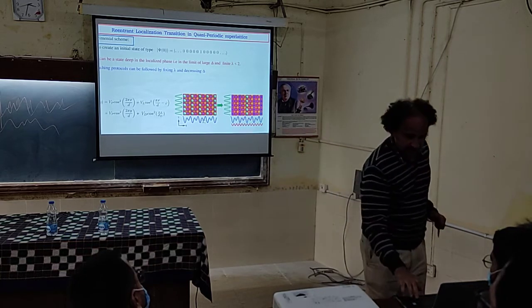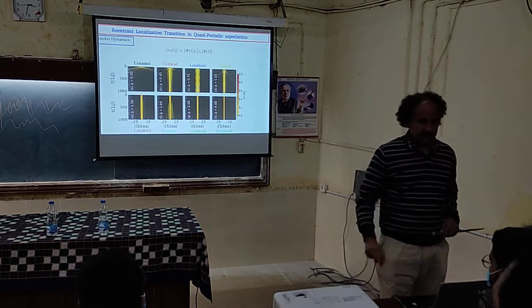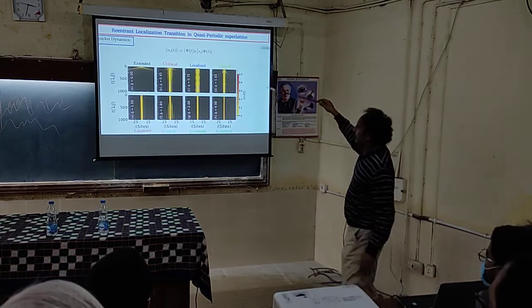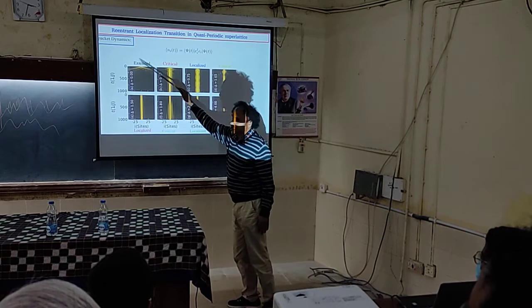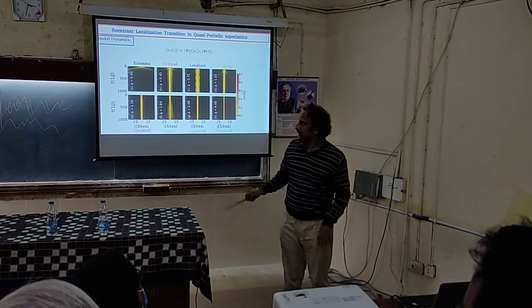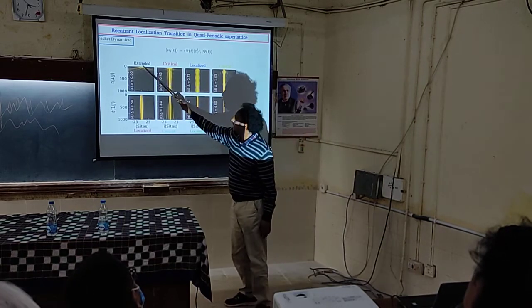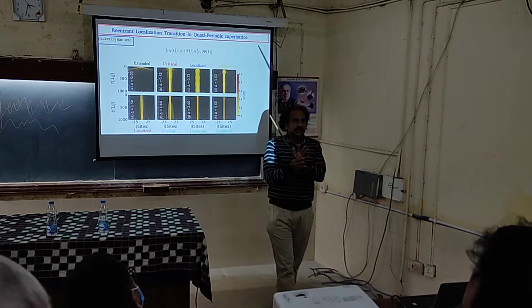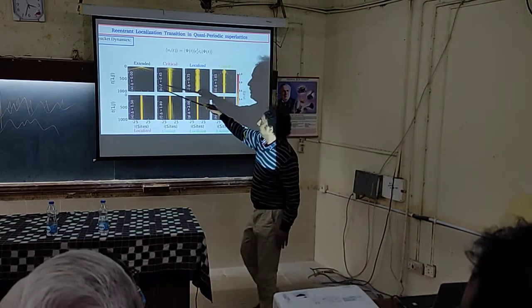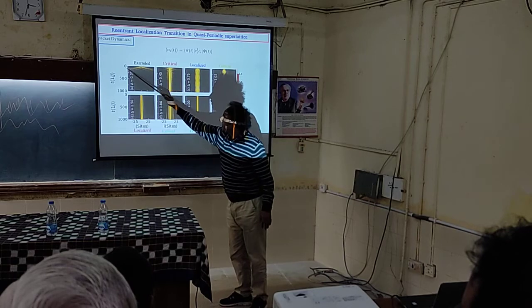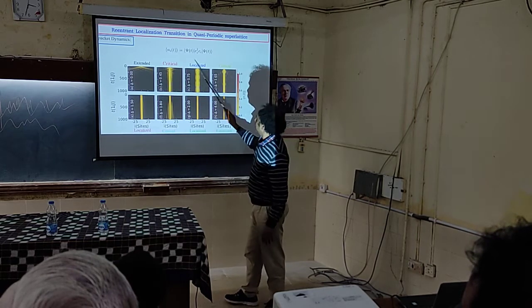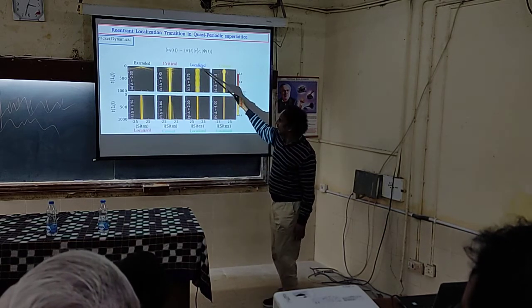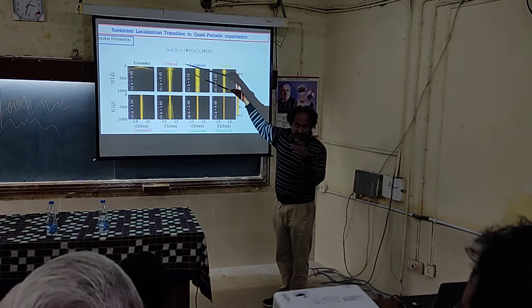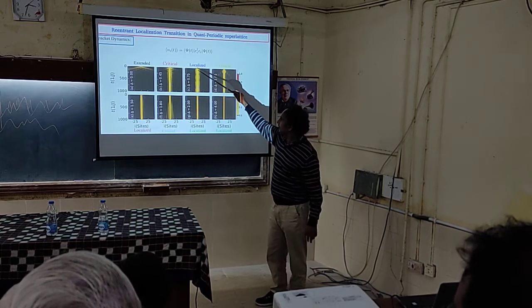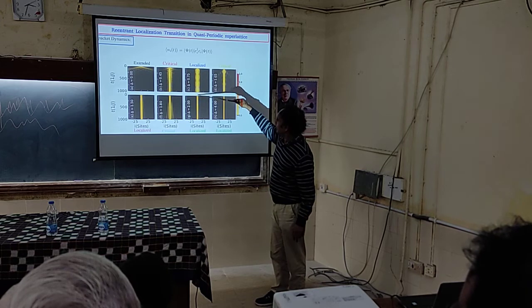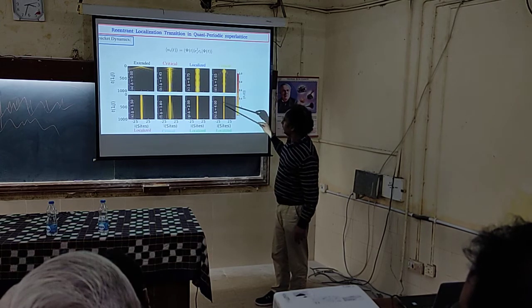If you time evolve, this is the quantum walk. If the states are extended, that means your disorder is such that you are in the extended phase, you can see the walkers spreading fast, reaching the boundary very fast. Then when you go to localized states, they are not spreading at all. They remain near the central site. So there is no spreading there, no spreading there.